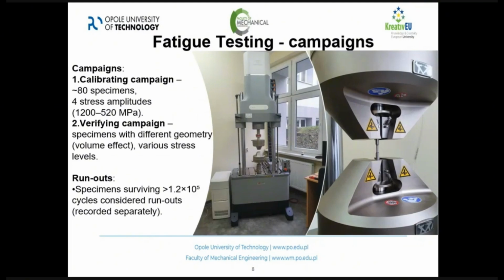So we did 2 testing campaigns. The first one was a, let's say, calibrating campaign. It was 80 specimens on 4 different stress amplitudes from 520 to 1,200 megapascals, 20 specimens each level, just to get a calibrating curve for the model.